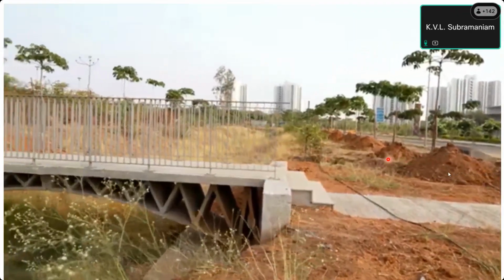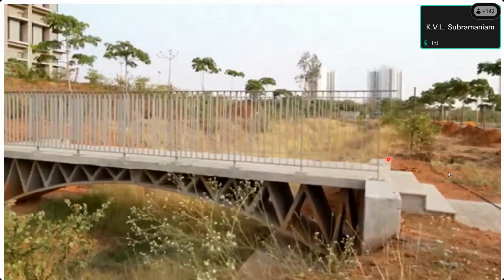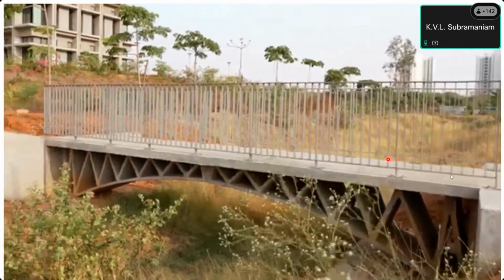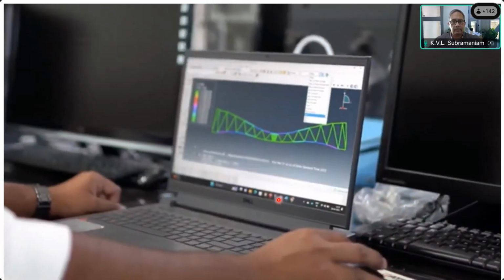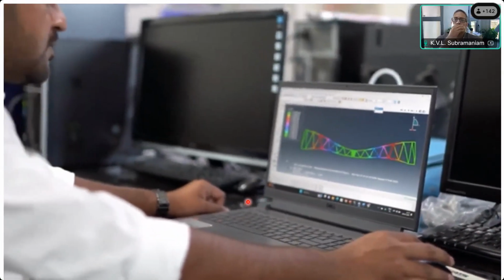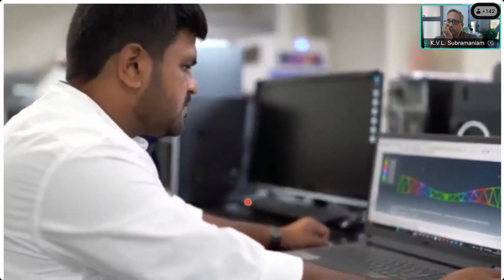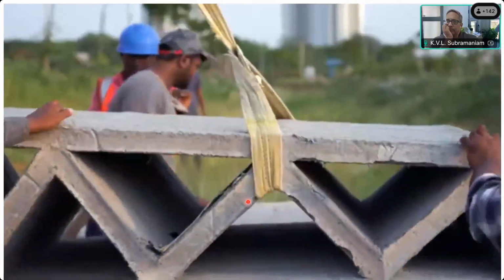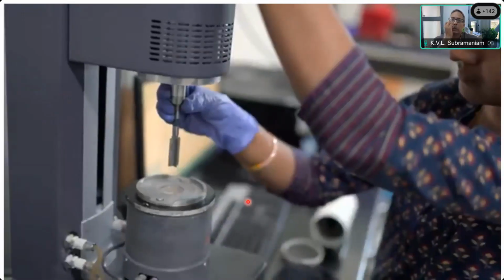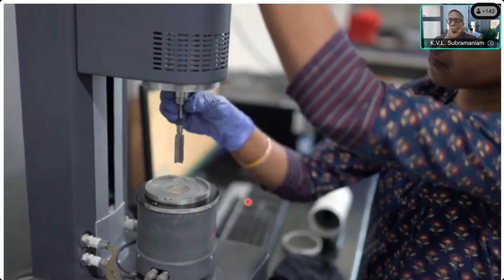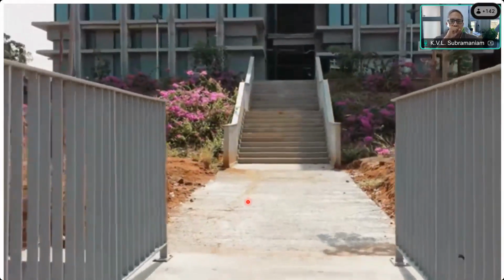So the 3D printed bridge installed at IIT Hyderabad is a 7-meter long bridge, which was built in 2 parts. It had minimal reinforcement and was built in a compressed arch geometry. Talking about the geometry, IIT Hyderabad had developed the geometry in multiple iterations, keeping the printing path in mind. The bridge was printed using Simplicrete, the material which is indigenously developed by Simply Forge, and it was extensively tested for rheology and other parameters by IIT Hyderabad for the qualifying criteria of the bridge.